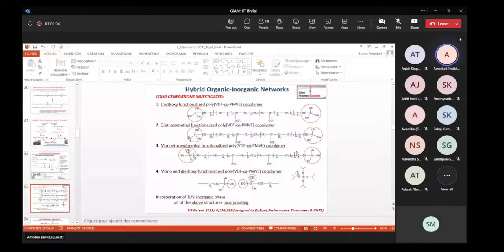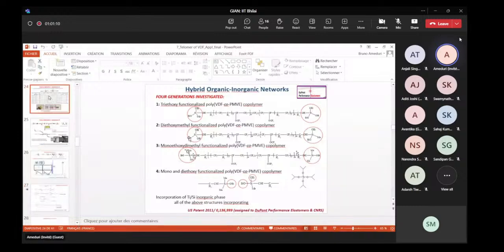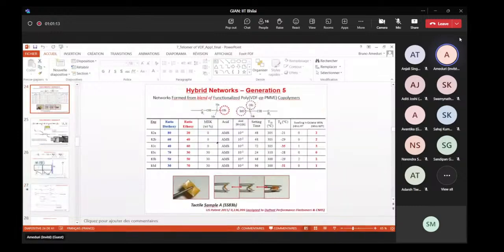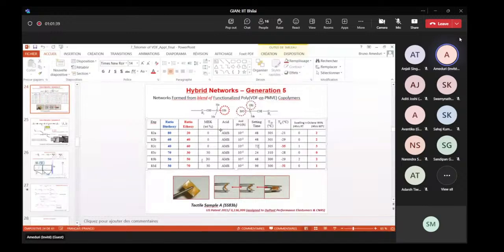So this was nice. We had a lot of results, and indeed, from this application, the best system was to find this monoalkoxy and dialkoxy, to change the ratio also, so you can imagine how many attempts we did in this work to use or not some methylated ketone, different acids, methanesulfonic acid in different concentrations, setting time. It was a little bit long, 70 hours, but the good thermostability and the Tgs could be improved. The best one was -35, but for DuPont, this was a little bit high.